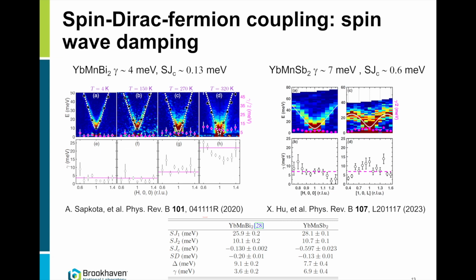One way to look for it is to measure the damping of the spin waves, and we did that in ytterbium manganese bismuth 2 and ytterbium manganese diantimonide. And we were able to refine a very tiny damping. I'm still not 100% convinced, since it's at the edge of what we can do in neutron scattering with this sort of energy scales. So the tiny damping in the ytterbium manganese bismuth 2 and the interlayer coupling, of course, is another evidence that the magnetic moments are coupled to conducting layers, because the coupling between magnetic layers has to go through the conduction layer. So there is no way it doesn't involve Dirac electrons in the conduction layer. As this damping increases from the bismuth material to the antimony material, the interlayer coupling also increases. So this seems to be consistent with an increase of coupling between magnetic moments and Dirac electrons as you go from ytterbium manganese bismuth to ytterbium manganese diantimonide.